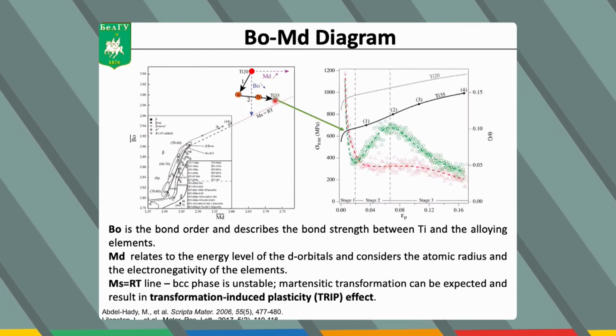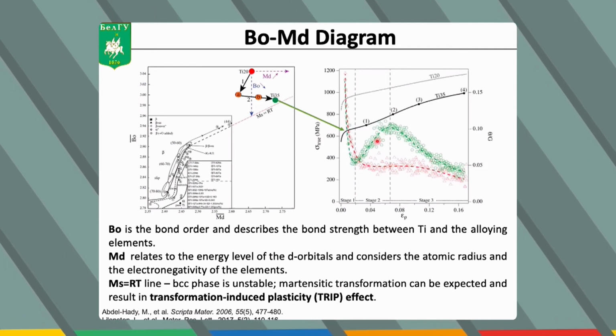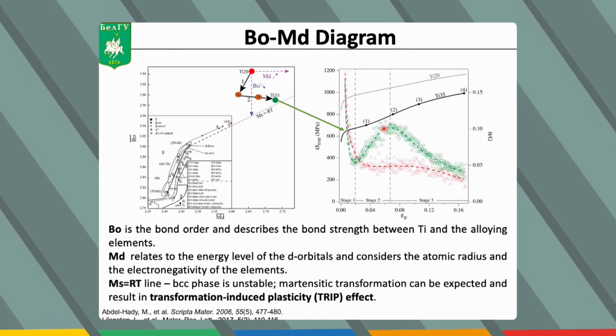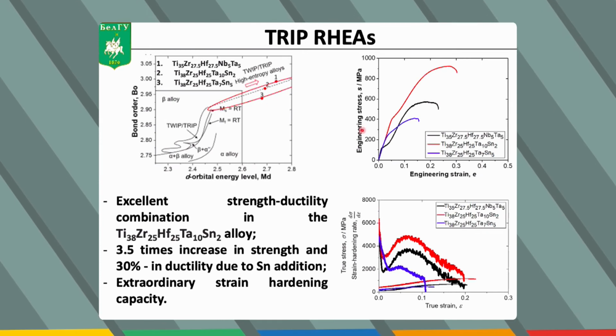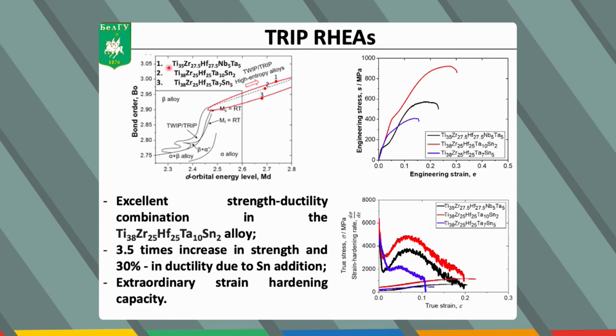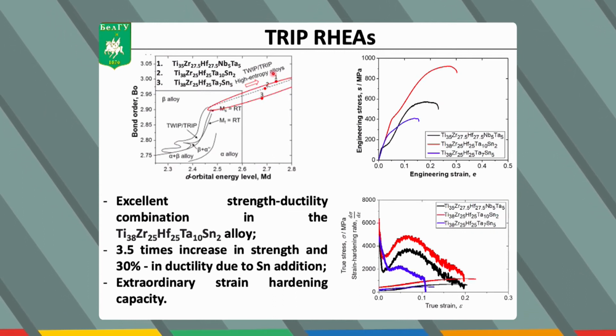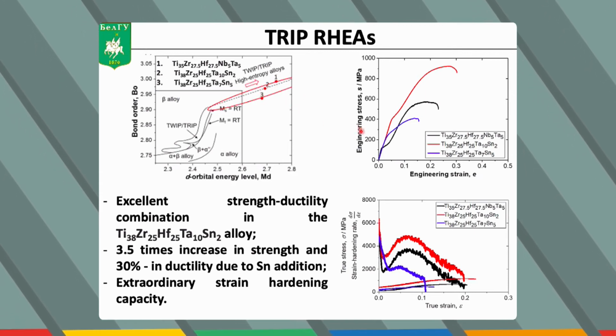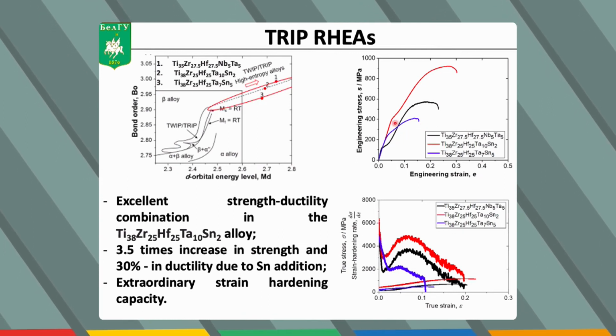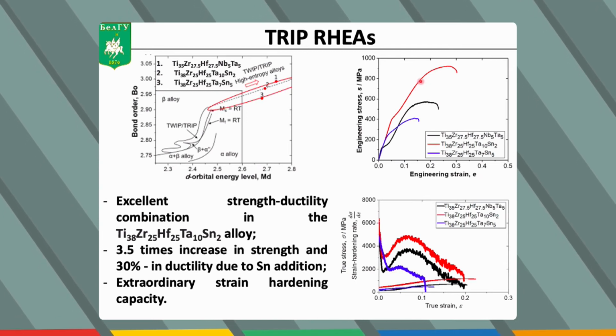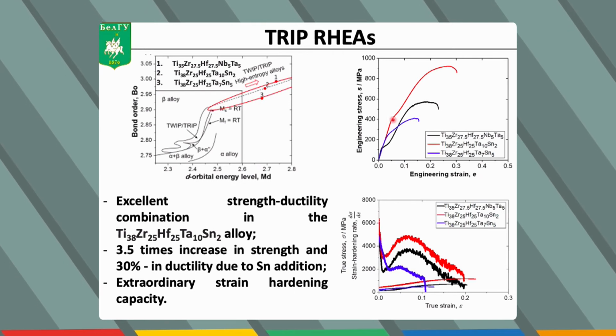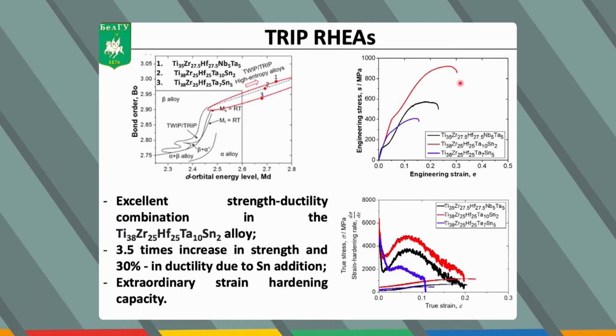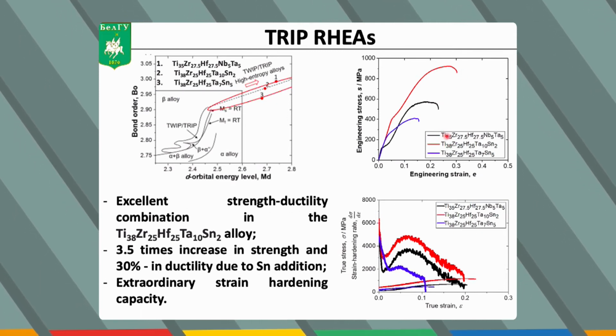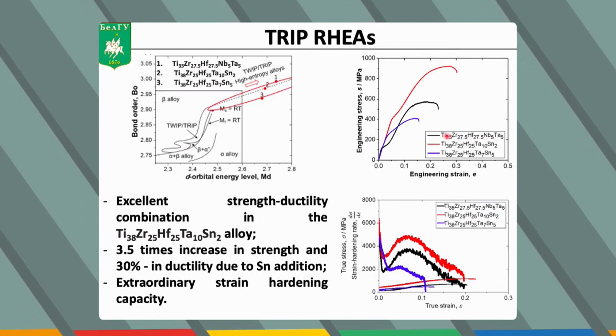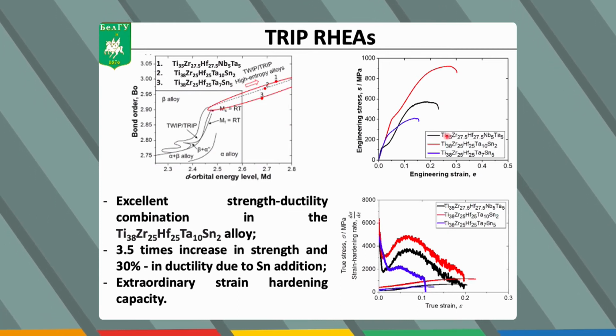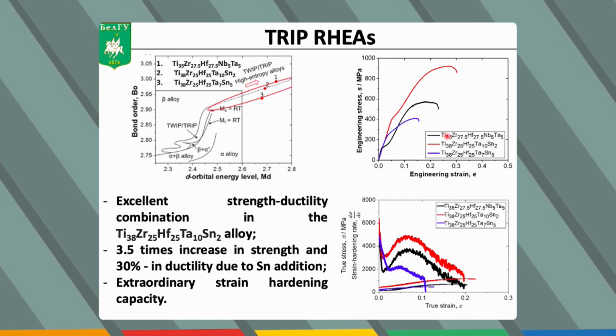And some alloys close to this line were developed, and they indeed demonstrated increment in strain hardening and some increase in ductility. But we wanted to go further, and we have introduced a new set of alloys. All of them were quite close to this line corresponding to the TRIP effect. And here are the mechanical properties of these alloys. And you can see that at least some of the alloys demonstrate really nice properties. The second alloy, demonstrated by the red line, has very nice strength, just enormous strain hardening capacity, and nice ductility. And if we compare it with the previous alloy, we can see that the simple addition of a small amount of Sn, 2 atomic percent, results in 3.5 times increment in strength and also some increase in ductility.